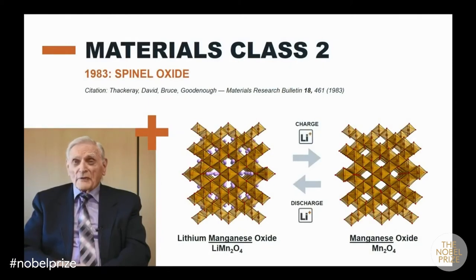And then a man from South Africa by the name of Michael Thackeray came to my office in Oxford and said, I want to use the magnetite, because that's a cheap material for lithium insertion extraction. And I said, well, I would like to see if you could do it in my laboratory, because normally spinels are line phases, and so I'm surprised that you can put lithium in and out of magnetite and still have the same structure. So he did that in my laboratory, and then I said, well, that's fine, but what you need to do is to go to a manganese material so you can put the lithium in and out without having to push some of the lithium out as a separate phase on the surface. So that's how Mike Thackeray and I started to work on the lithium manganese oxides.